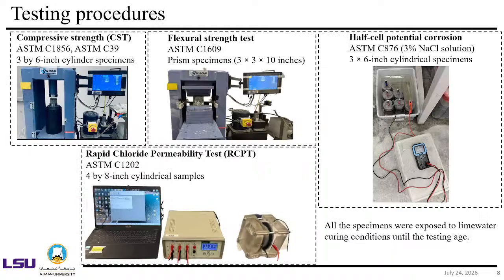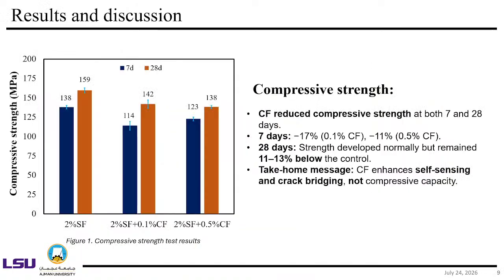Apart from that, we also did some mechanical performance testing, including a very typical compressive strength and flexural strength, and some other durability tests, including rapid chloride and half-cell potential corrosion. So here come the very interesting results.